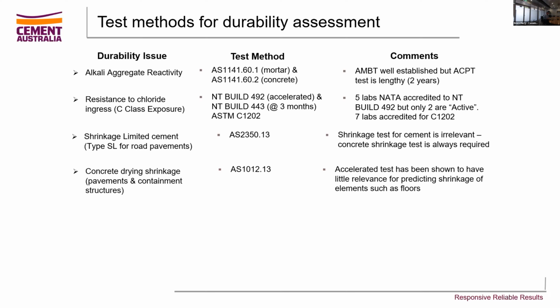Thank you. Concrete drying shrinkage. This is another accelerated test, and it's primarily aimed at concrete mixes that are used for pavements, floors, slabs, etc., and also containment structures, water retaining structures, even radiation containment structures. Now, this is an accelerated test that's well documented in AS 1012 part 13, but the test has really a lot of limitations, and not least of which is the fact that the results you get in the accelerated laboratory test really bear little resemblance to how a concrete element will perform in the field.